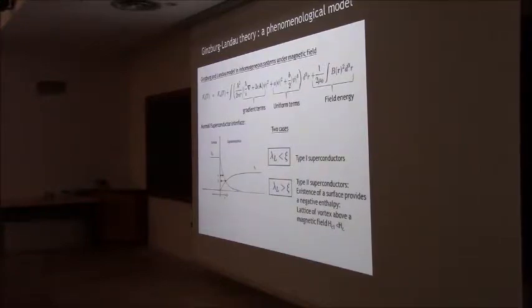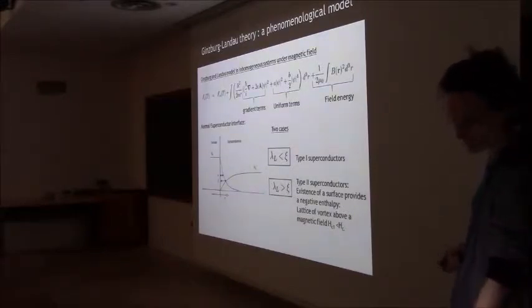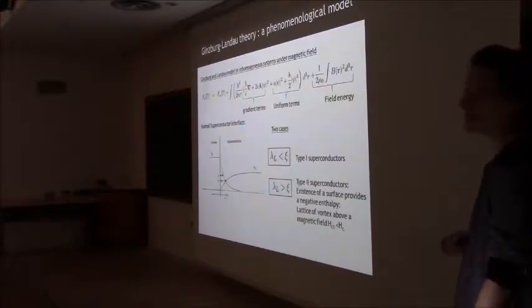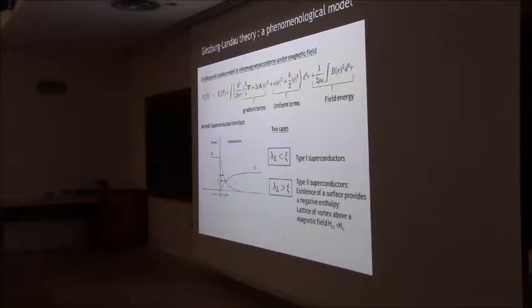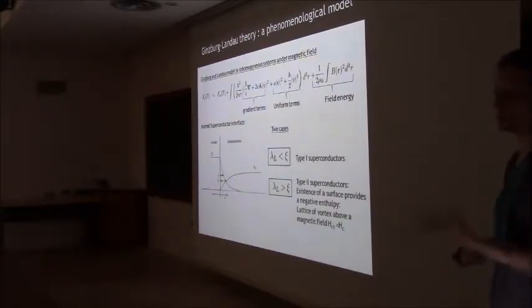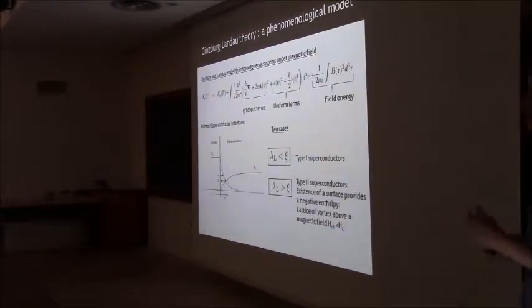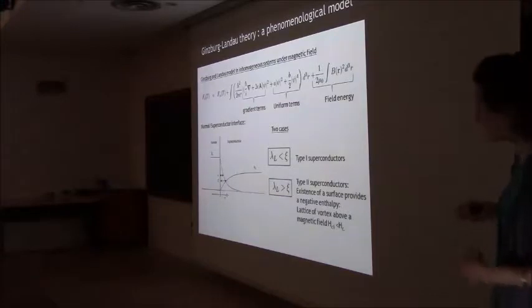Inside the vortex it's a normal state, and outside it's superconducting. Then you have this interface and you gain a lot of energy. And these vortices, they see each other. It makes a kind of crystal, a lattice. And then you get a very nice lattice of vortices when you apply magnetic field above Hc1. So for comparison, Hc1 is smaller than the thermodynamic magnetic field we saw just before. So in fact, there are a lot of superconductors which are type 2, and the study of the vortex lattice is also a field in superconductivity, because you can get a lattice, you can also get a liquid of vortices, and the shape of the lattice of vortices gives you information about the superconducting state, about the shape of the order parameter. So it's a very lively field also.